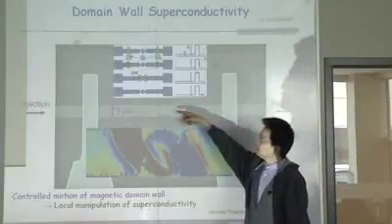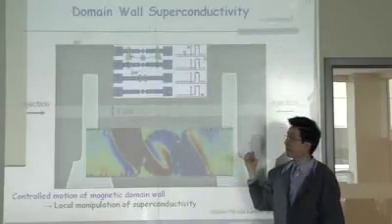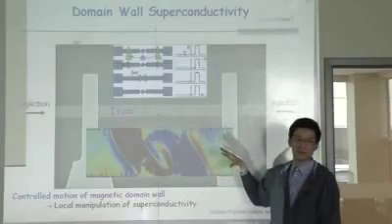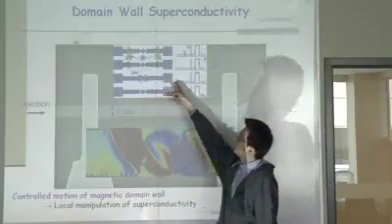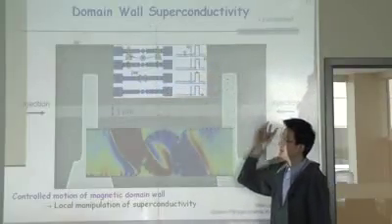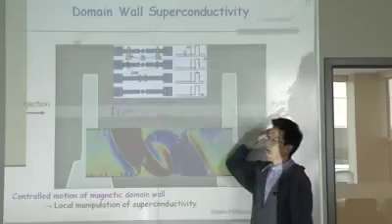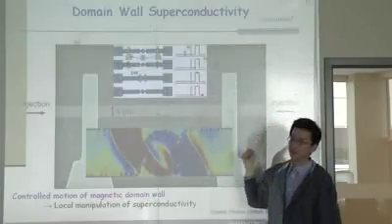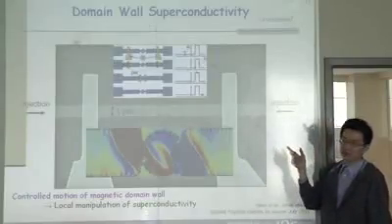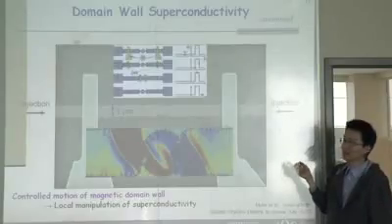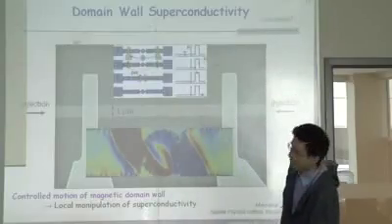And when that happens, these magnetic domain walls will generate a local magnetic field that will suppress superconductivity. Here, the inset shows you a mapping of the field distribution around this domain wall region. So when that happens, we are going to see a high resistance state in the wire. And if we apply large enough energy to drive the domain walls out of the system, it will return to its low resistance state. As you can see, not only can we control the superconductivity very nicely, we can also do it precisely and locally whenever we need and wherever we need.